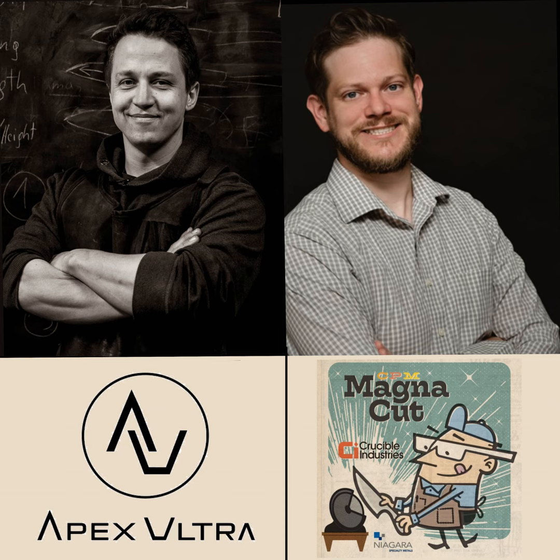But there's pros and cons. If you have good results with coffee, just stick to the coffee. But I got brownish tones every now and then. Yeah, we do too. But it also depends on the brand of coffee. We use the Nescafe, I think it's called dark or strong roast or something like that. So the instant coffee. But I'd rather have something else because the coffee is always messy. One advantage of the coffee is it holds up a lot longer than the orange juice. You have to throw away the orange juice after about a week. Okay, 4 or 5 days. So if you work in batches, not a big problem. It's €2 for 2 liters or something like that, and then you can etch your blades and it's good. But if you do one knife and then in 4 days the next knife and it's already broken, it's not working anymore, then it's a shame.